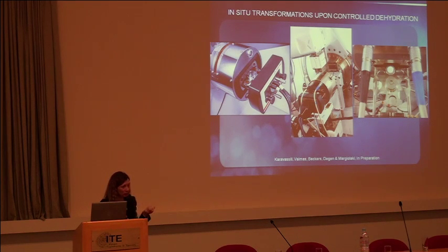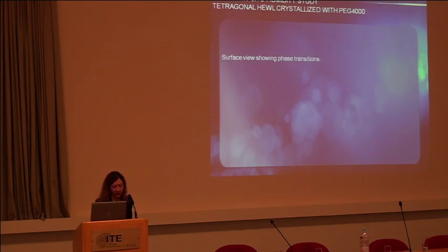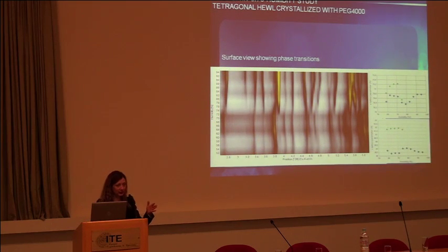I wanted to do the same on a protein, but I was missing this chamber. And this chamber was produced by Anton Paar a few years ago. We adapted the chamber on a lab diffractometer, and we loaded our protein samples, which looked like this. So we vary the relative humidity, and we collect data in order to observe any structural transitions. We started this experimental work with tetragonal hen egg-white lysozyme simply because it crystallizes very quickly and very robustly, and we didn't expect to see any structural changes upon humidity variation.